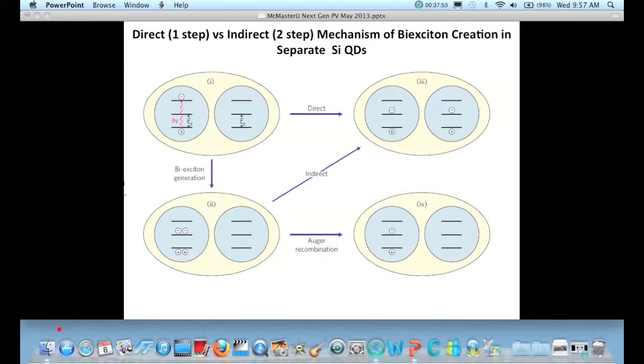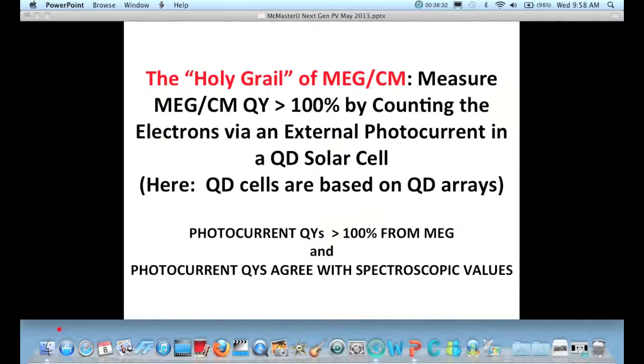This was a big surprise, because our belief was that first you have to absorb the high energy photon, you create 2 electron hole pairs in the same dot, and then they separate in your device to give you 2 excitons that are separated, and then you break the excitons apart at the interface with, say, the ohmic contact, or in the p-n junction, the nanocrystalline p-n junction in the cell, and then you collect the carriers. But this direct mechanism is very interesting, and the process is very efficient. So this has to be followed up to see what that means.